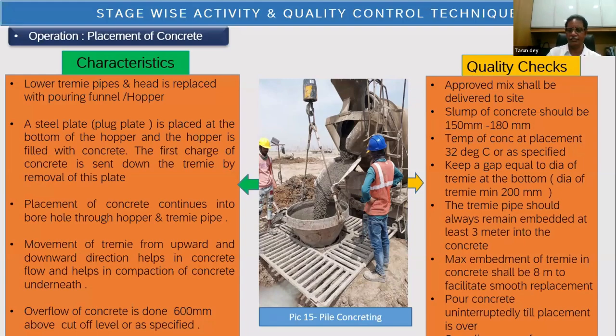So these are the various checks at the concrete placement stage. And you face a lot of problems if all these things are not maintained. There are people who get guided by the flow instead of slump, because slump is quite indicative. In that case, flow could be 550 to 600 millimeter while you are placing concrete. And this concrete necessarily is self-consolidating type, because you are not able to vibrate it by taking the tremie up and down. We are not vibrating the concrete, we are not compacting the concrete. So it should be self-consolidating type. And the retention should be higher.